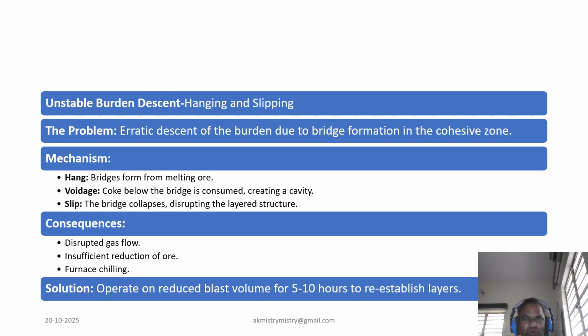Now let's talk about the rhythm of the furnace: burden descent. When this becomes unstable through hanging and slipping, the entire process is jeopardized. The mechanism is a three-act drama. Hang: bridges of semi-molten ore form in the cohesive zone, as we have discussed many times in our earlier presentations, supporting the weight above. Voids: meanwhile, coke beneath these bridges is consumed, creating a hidden cavity. Slip: the bridge suddenly collapses due to continuous consumption, violently disturbing the carefully layered structure inside.